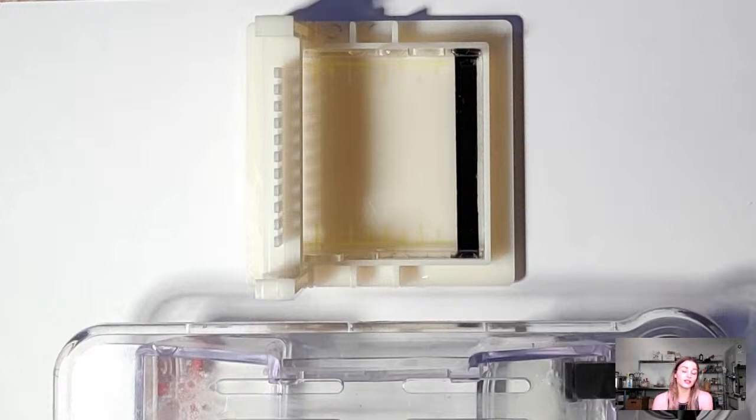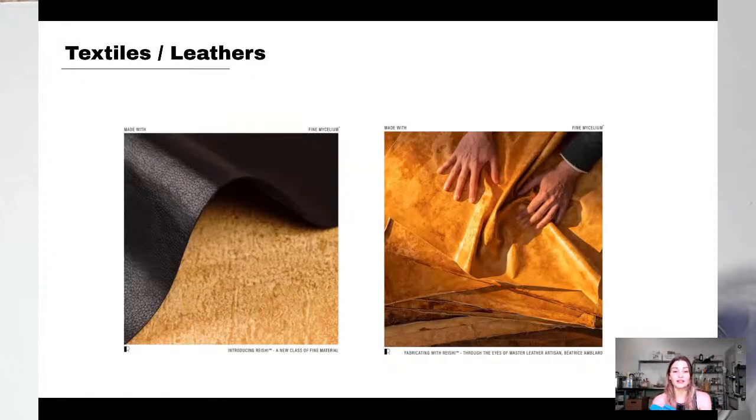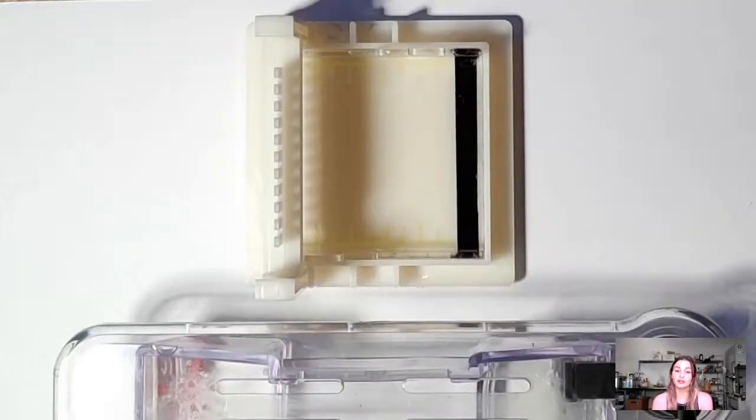But essentially, they're engineering or encouraging the fungus to really express that mycelial weaving. As you saw in the picture before, it's kind of like felting, a very matted, involved matrix, and that creates great structure for a leather-like material. But it does require some cross-linking, and that chemistry can be difficult to do green.